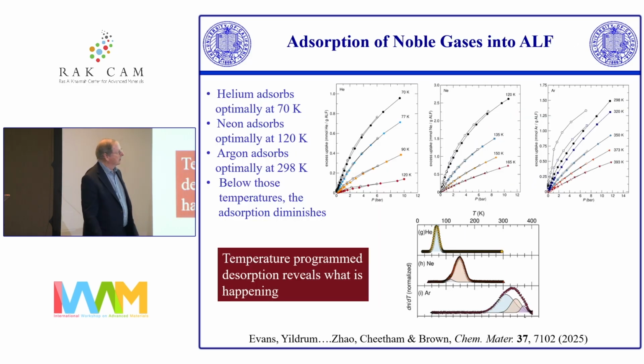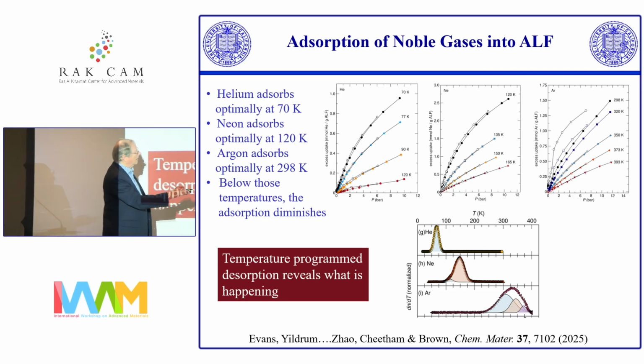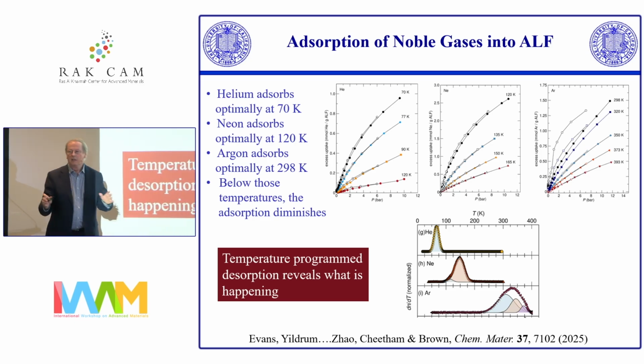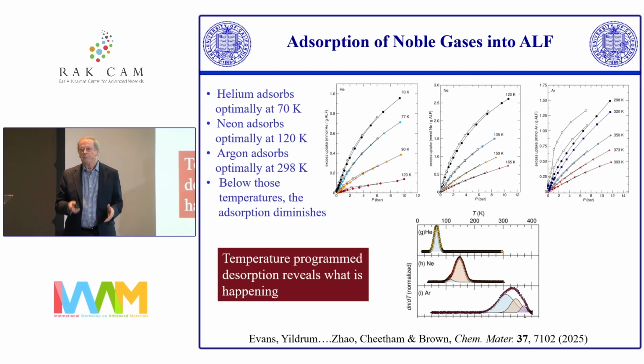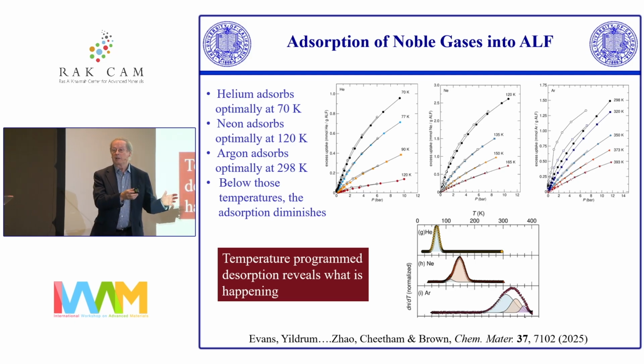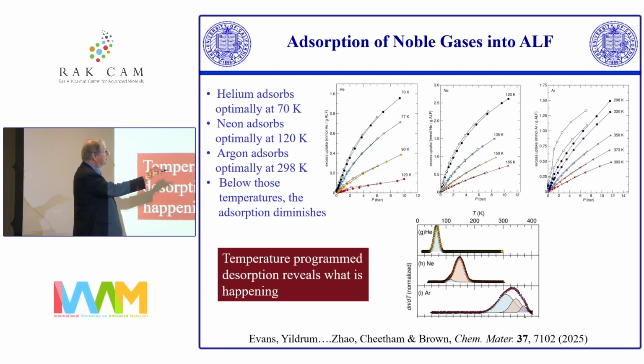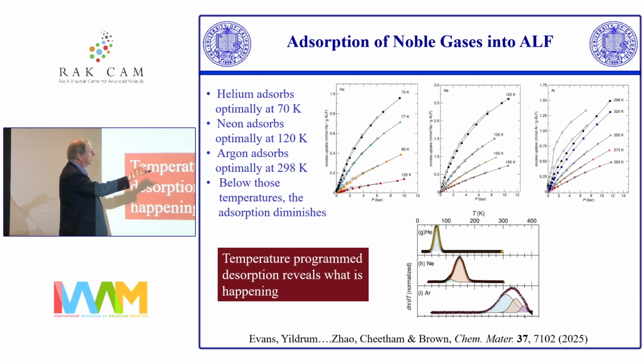So I'll quickly show you what happens with the inert gases. They show exactly the same effect, and these are some of the adsorption isotherms here. If you take helium, you have to cool it down to about 70 degrees Kelvin, and then it will adsorb. If you go down to 50 degrees Kelvin, it won't adsorb. So there's a very characteristic temperature for helium adsorption. Same for neon, and the same for argon. In the case of argon, it's sort of above room temperature.